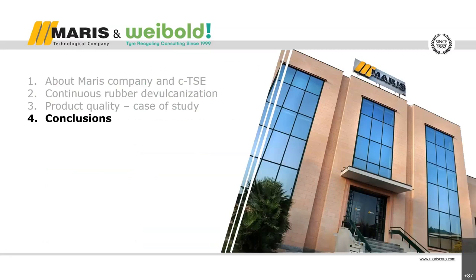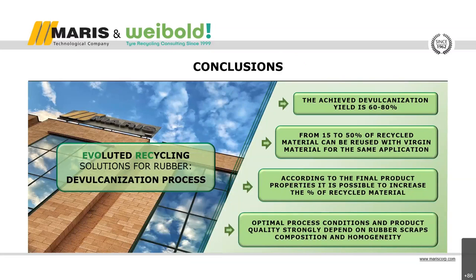Now, I'd like to end with a summary of the main points. As we have found experimentally, the actual devulcanization yield is between 60 and 80%. According to our experience and our customers' results, from 15 to 50% of a recycled material can be reused with virgin material for the same application. Then, according to the final product properties, it is possible to increase the percentage of recycled material. And finally, optimal process conditions and product quality strongly depend on rubber scrap composition and homogeneity.